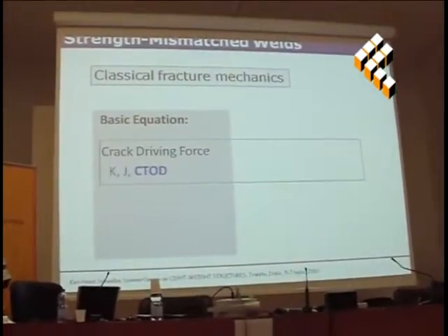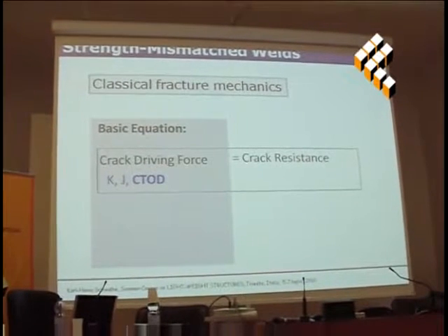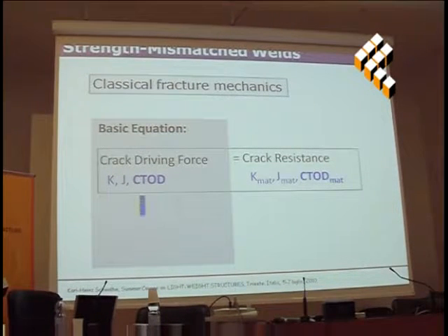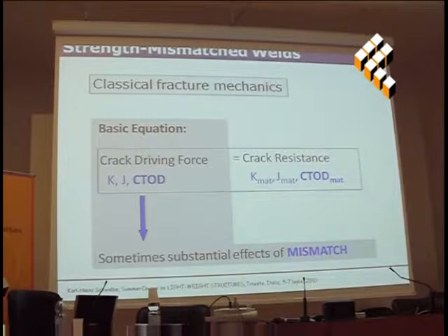Now, continuing here. This is again the left-hand side, the crack driving force. On the right-hand side, you have the resistance. And we will see that the mismatch can have a huge effect on the crack driving force. By huge, I mean an order of magnitude, which is normally not in people's minds.